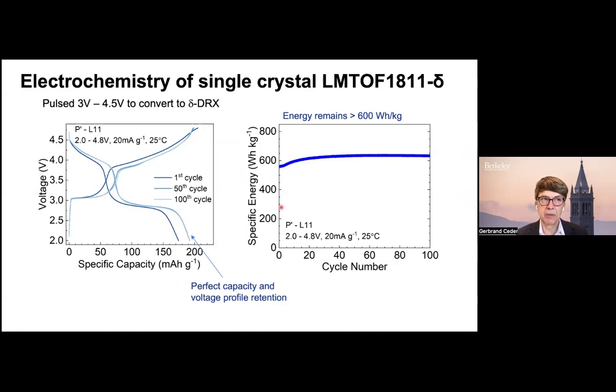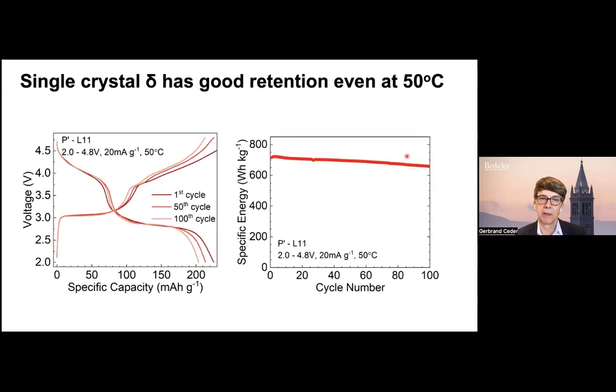And you see that in the specific energy. If you start cycling the material after formation, the specific energy creeps up a little bit because of the remnants of the formation. Then here it taps out and is flat at about 625 watt-hours per kilogram, which puts you at the low end of the NMCs, well above lithium iron phosphate.